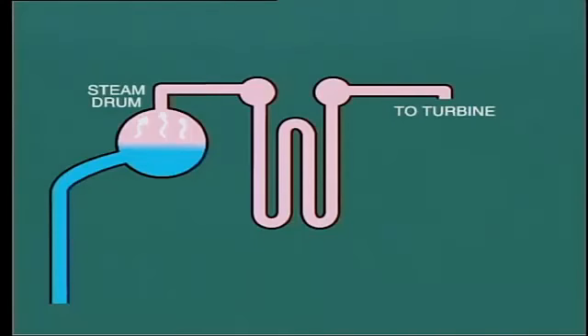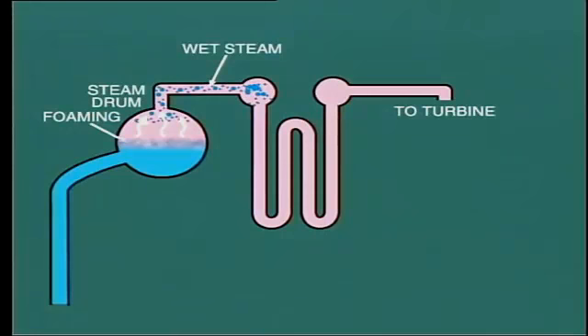The addition of trisodium or disodium phosphate to the boiler water does have some negative aspects. For one, it adds yet further solids to the water. In addition to this, it will affect the pH value of the water, and this may aggravate corrosion. We'll discuss this later. Another problem associated with high solids content in boiler water is carryover. The effect of the dissolved and suspended solids is to increase foaming on the surface of the water in the drum. This, in turn, leads to carryover of water with the steam.